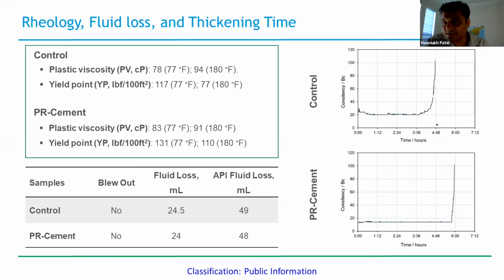And here on the right side, you can see the two plots of control and polyrotaxane. The control starts curing after about 5 hours, and the polyrotaxane cement mixture starts curing at about 5:45 hours. So the curing times can be tailor-made based on different additives available in the market. We can use a retarder to delay the curing process, which is the transition time of the cement slurry.